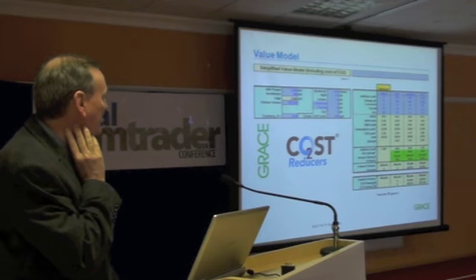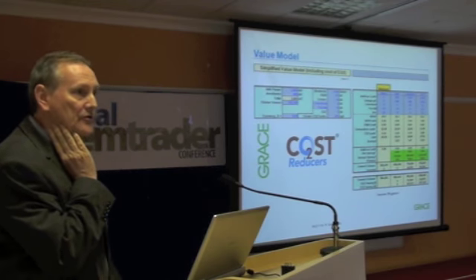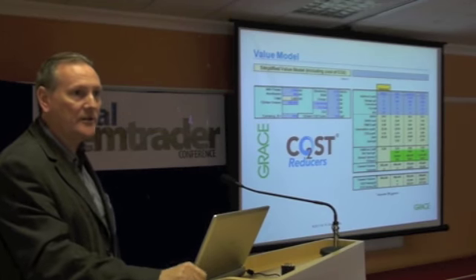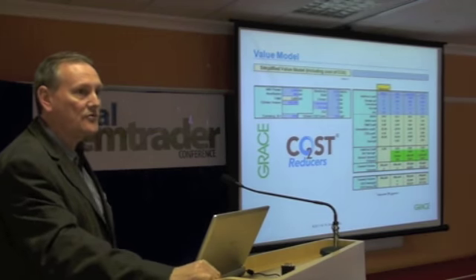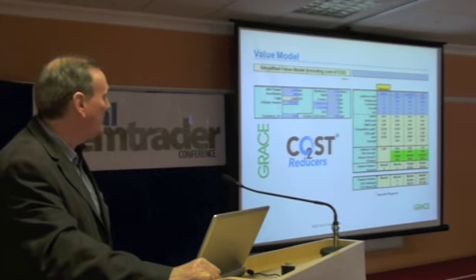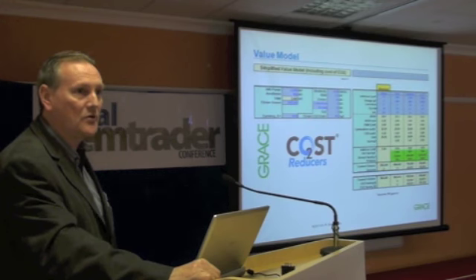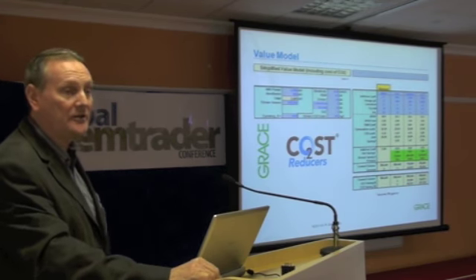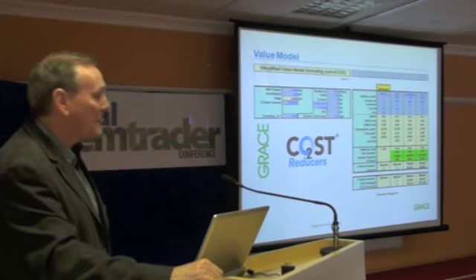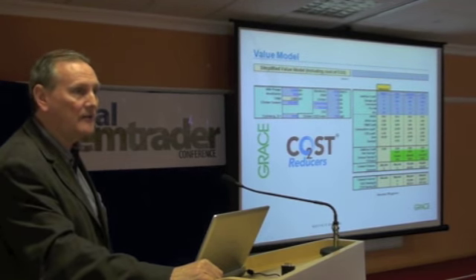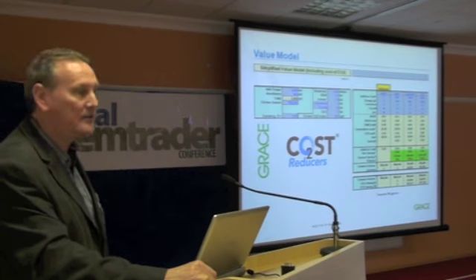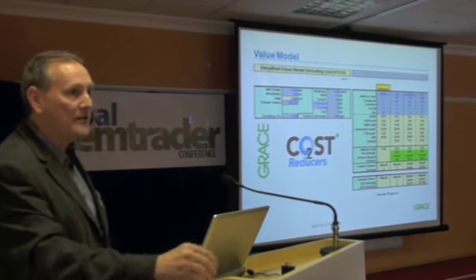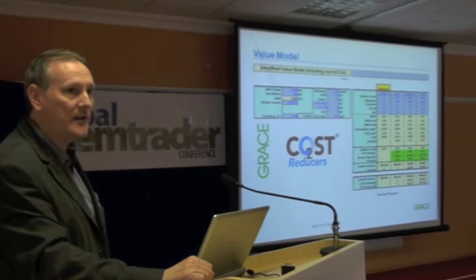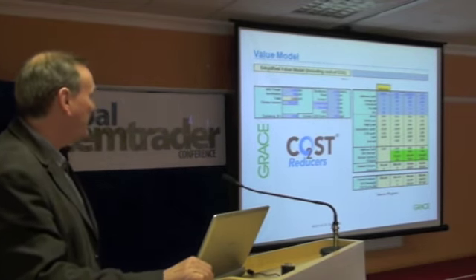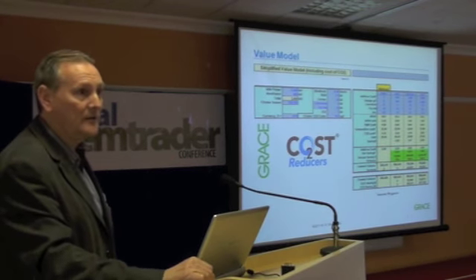The usual benefits we're looking at are the energy costs. Cement grinding is 30-40 kilowatt hours per tonne, which of course, with today's increasing electricity cost, has a cost. If you increase the output of a grinding system with more or less the same kilowatts, then your specific energy consumption per tonne of cement is going down. There may be associated repair and maintenance costs with running grinding systems. If you make the same volumes in less running hours, you spend less wear and tear on the system. The big saving can be the differential cost between the SCM and the clinker. And in this case, we've also included the CO2 where relevant.